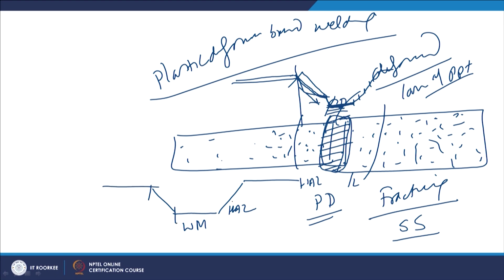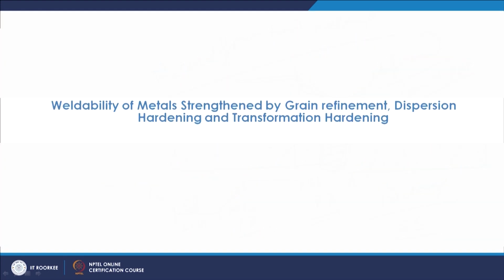So, this reduction in the hardness in the heat affected zone is due to the partial dissolution, while in the weld metal the minimum hardness is attributed to the complete dissolution or complete reversion of the precipitates. So, these are completely different aspects from the weldability point of view of the work hardenable and precipitation hardenable metal systems. Now, we will see the way by which the metal is strengthened by grain refinement, dispersion hardening